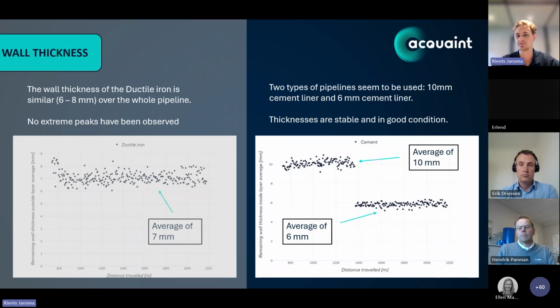So an interesting thing for the cement liner is there have been found two types of cement liner. The graph is the same as the ductile iron one, only it's just the first few hundred meters of the ductile iron had a cement liner of 10 millimeters. And the following section is around 6 millimeters. The thicknesses are stable for both cement liner and the ductile iron, which means it's in a good condition.